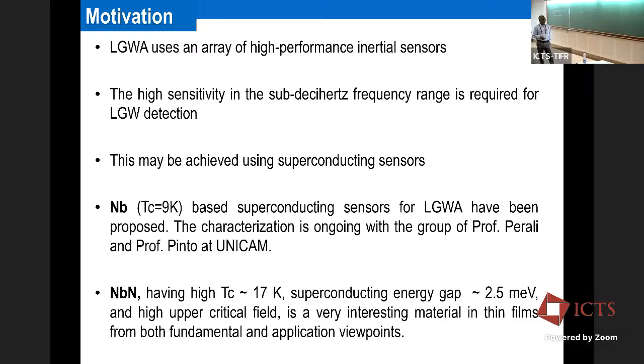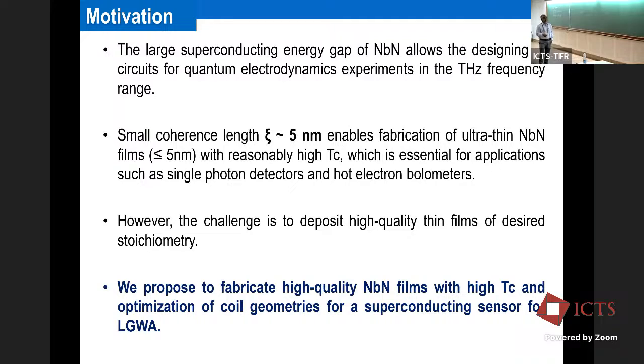And recently we have developed these NbN films with high TC of around 17K. This material has a superconducting gap of 2.5 milli-electron volt and a high upper critical field, which makes it very interesting from the basic science point of view as well as the application point of view. The large superconducting energy gap allows the design of circuits for quantum electrodynamics in the terahertz frequency range, and the small coherence length of around 5 nanometer allows us to have very thin films with high TC without any kind of phase fluctuations. So these films are very useful in single photon detectors and hot electron bolometers.